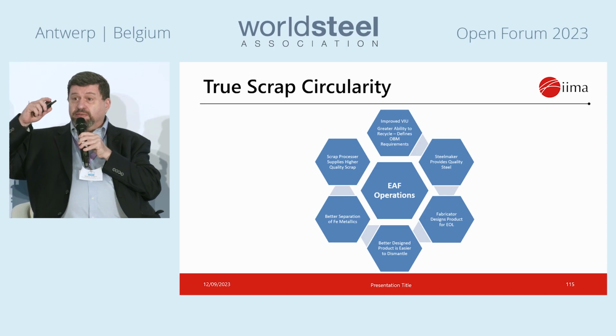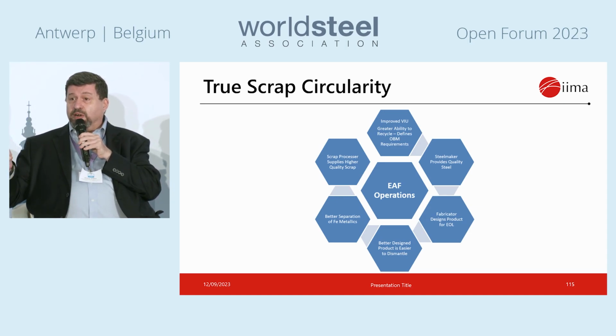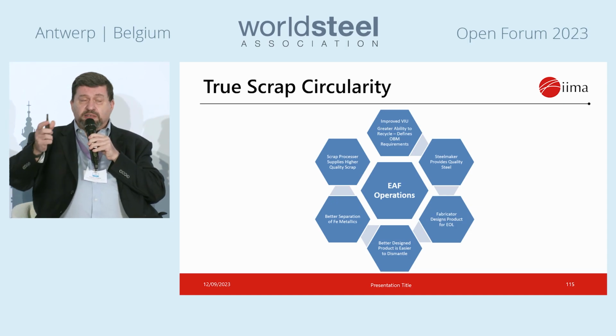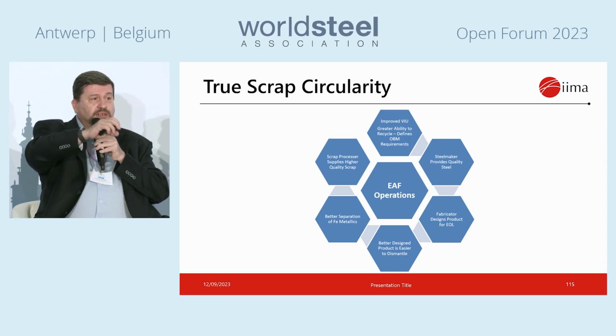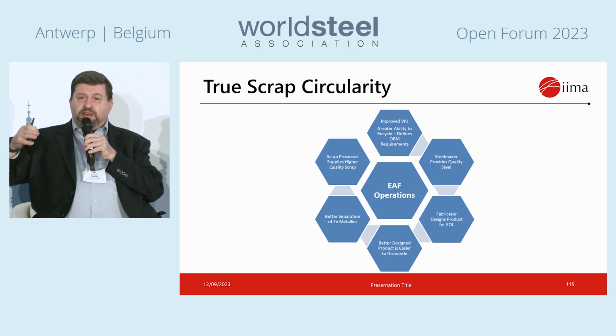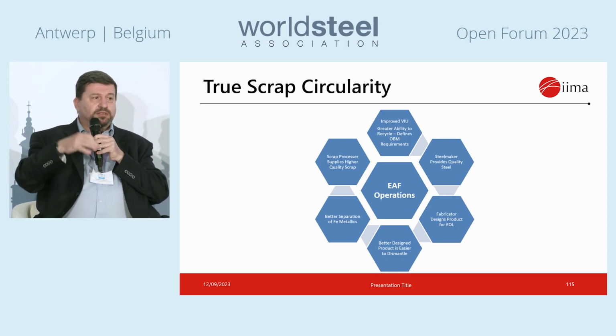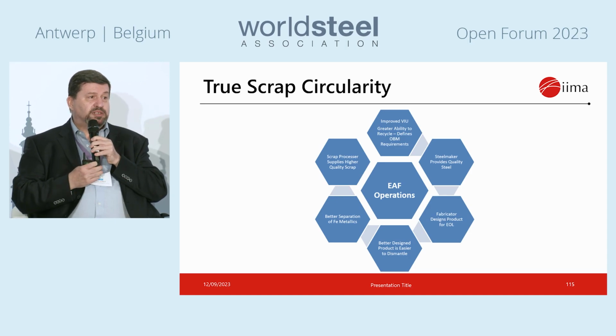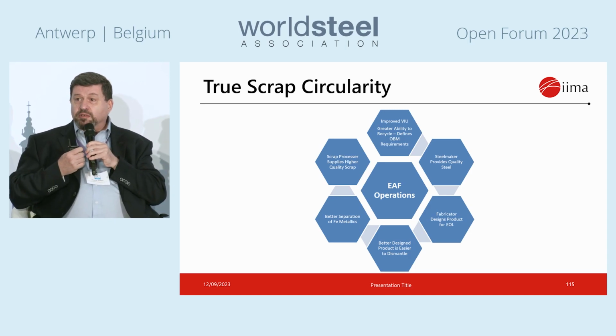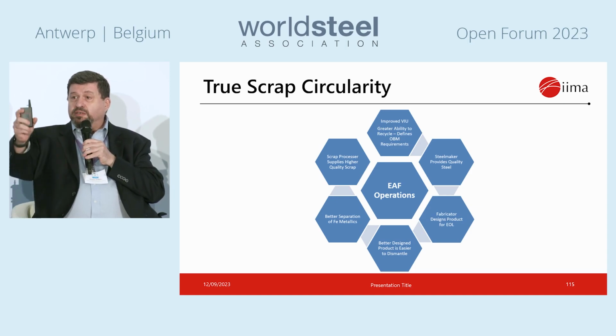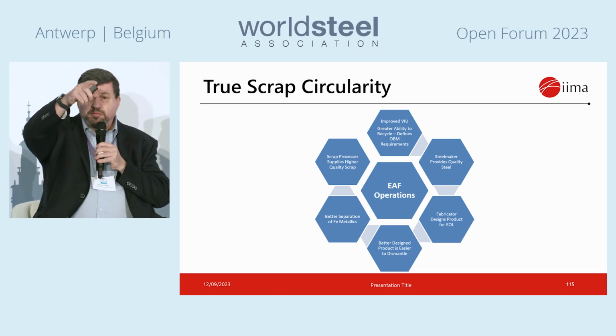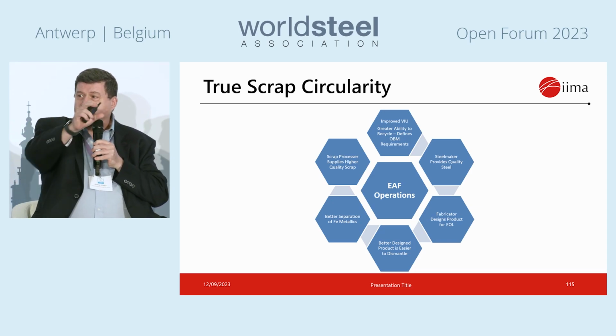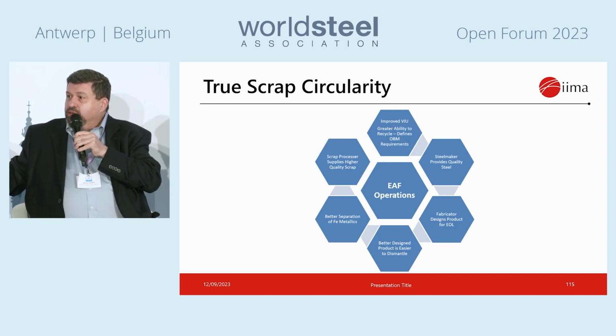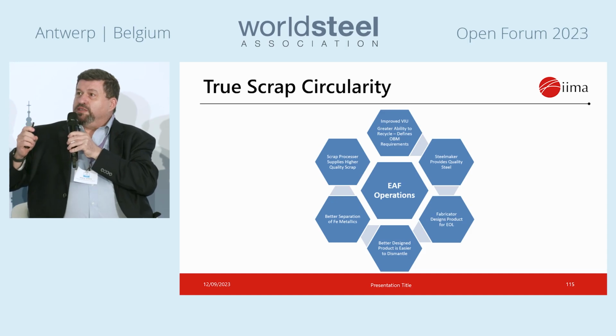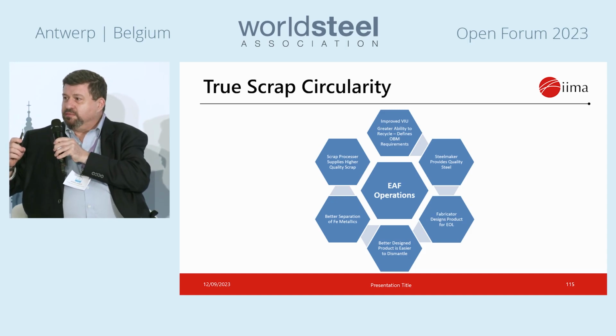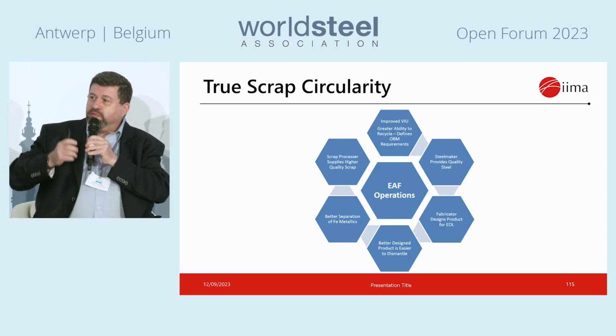So that means when you have an electric car that has 6 to 8 times as much copper in it as a conventional car, basically the way that the car is laid out, where the wires are, where the copper battery is, all these things are designed in a way that they can easily be removed before that car goes into a shredder. To me, that's just common sense. We also have an idea within our group that appliances should have a QR code. You scan it, it tells you exactly, remove this screw, this screw, take this out, take that out. And again, now you're optimizing. And the problem is that manufacturers don't realize by not doing this, they're making it more difficult for the steel maker to provide them with the product that they want.